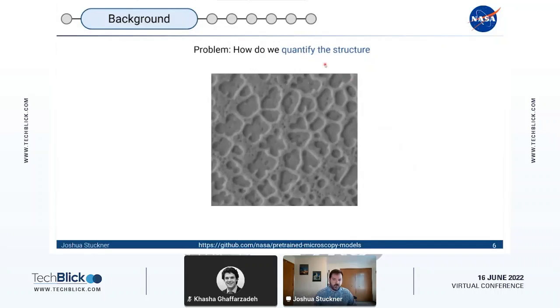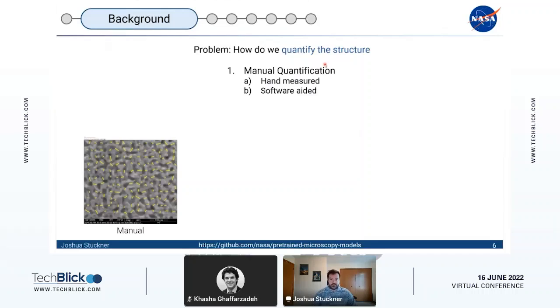The question is, how do we quantify the microstructure of a material? Traditionally what we've done is hand measurements where we maybe use software to draw a bunch of lines to measure ligament diameter, or there's ASTM standards to use the intercept method to get grain size analysis. But there's a lot of potential for bias here where different researchers may select different places and measure in different places. It's also extremely time consuming and tedious. So automatic quantification can allow us to make repeatable unbiased measurements and capture a lot more data which we can use to feed models to establish the PSP relationships.